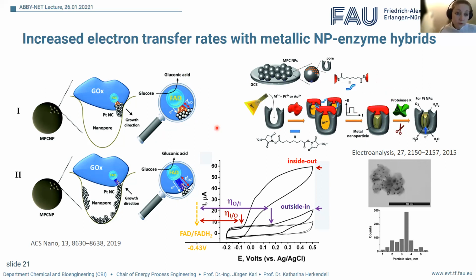Something even cooler we showed, as I think at least, was the incorporation of platinum salt, which we then showed either electrochemically, like the straightforward approach, would form platinum nanoclusters that would behave catalytically, as you see here in the outside in approach, by just growing nanoparticles randomly and then by chance also wiring into the active center and actually bridging the tunneling barrier. But we could also show that by enzymatic catalysis, we could actually grow the platinum salt in a direct bridge from the FAD towards the conductive surface, here called the inside-out approach.